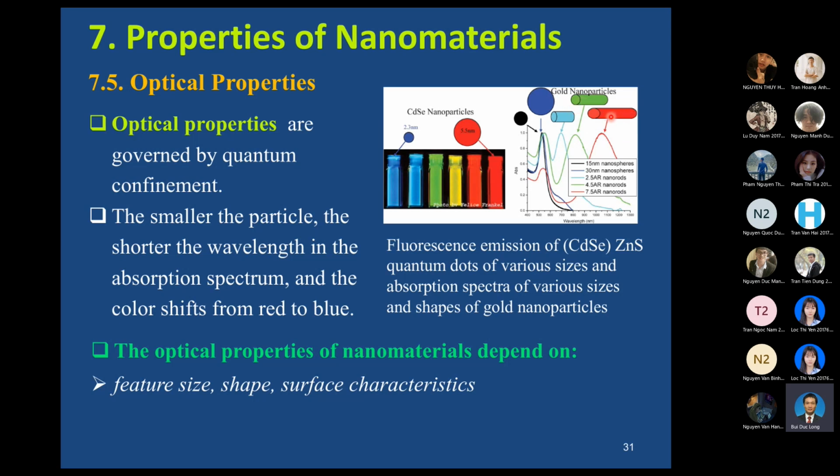or even the nanoparticle shape, geometry, the absorption spectrum will be different, and of course it will make a different color. You can see here different nanoparticle sizes, reduced from 5.5 nanometers to 2.3 nanometers, so the color will change from red to blue.